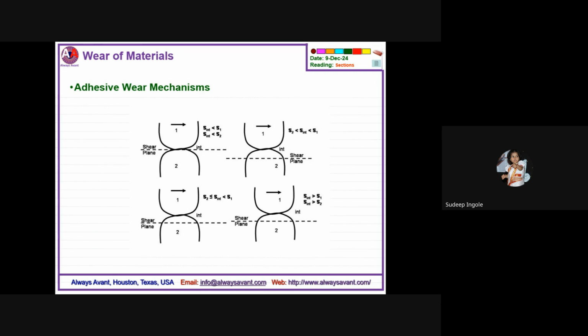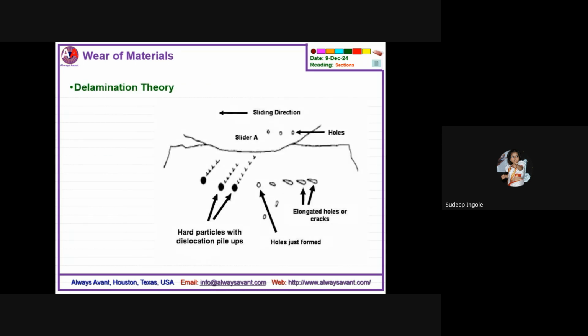And the 4th scenario is when the interface is significantly stronger than both of the sliding metals, shearing occurs at some distance from the interface. In such a situation, damage occurs from both the surfaces, and the surface damage increases as both of the sliding surfaces are damaged. And then there is another theory developed. The damage of the surface can also be determined by this theory, combined with Bowden and Tabor's theory, and this is called the delamination theory.